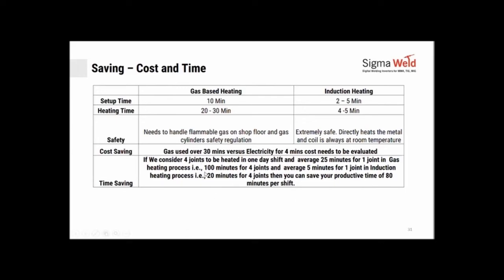If you look at the time saving, now this is where our focus will be more and more as you move along. Time today is going to be more valuable than money because you will have lesser time to produce more. Here you save straight away. Say you did 4 joints a shift, on average 25 minutes per joint in gas-based heating, and 4 joints you would have taken 100 minutes. 5 minutes for 1 joint in induction to do preheating. You could have done 4 joints in 20 minutes. 100 minutes for 4 joints with gas, 20 minutes for 4 joints in induction. 80 minutes per shift you can convert into productive time and get more jobs done. Same manpower, same equipment, more jobs done per shift.